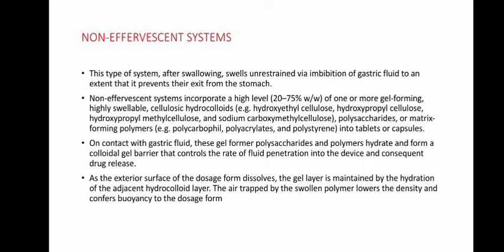On contact with gastric fluid, these gel forming polysaccharides and polymers hydrate and form a colloidal gel barrier that controls the rate of fluid penetration into the device and consequent drug release. As the exterior surface of the dosage form dissolves, the gel layer is maintained by the hydration of the adjacent hydrocolloid layer. The air trapped by the swollen polymer lowers the density and confers buoyancy to the dosage forms. As a result of this, the dosage form floats in the gastric fluids and releases the drug.